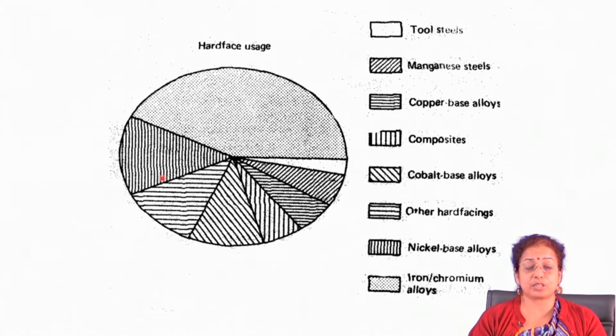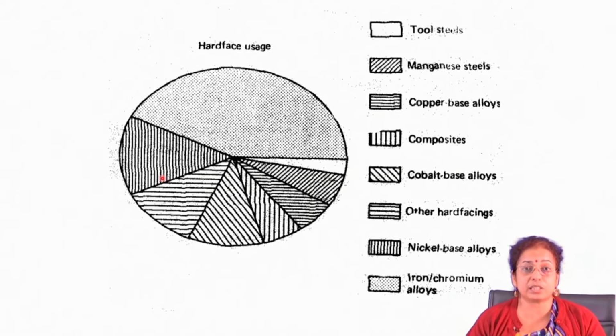It has been observed that if you develop a coating by plasma spray processing, and subsequently you melt it using a high power laser beam, you end up with a structure which is pore free and very nice, with improved corrosion resistance property on the surface. For example, it is observed that AISI 304 when subjected to thermal spray deposition of molybdenum will show deterioration in pitting corrosion resistance, but when the same coating is melted using the laser beam, you get very high pitting corrosion resistance of this coating. So, you can always go on combining two or three techniques to get the best result in terms of the desired properties on the surface.